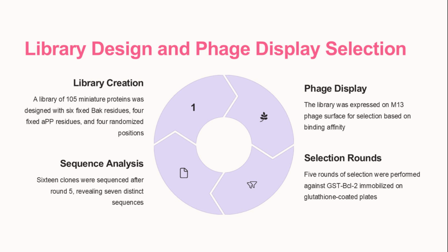The library was expressed on the surface of M13 phage, which enables selection based on binding affinity. 5 rounds of selection were performed, using GST-BCL2 immobilized on glutathione-coated plates. After the 5 rounds, 16 clones were sequenced, revealing 7 distinct sequences. This indicates the selection process was successful in identifying unique binders.